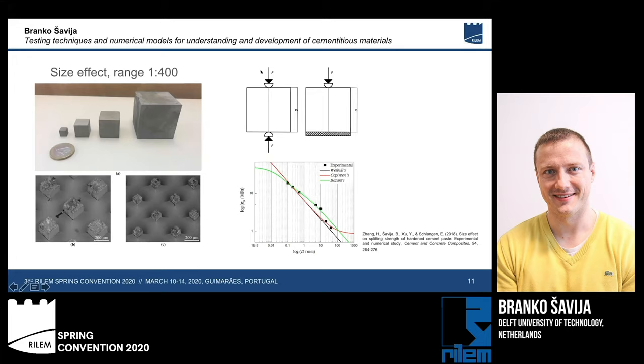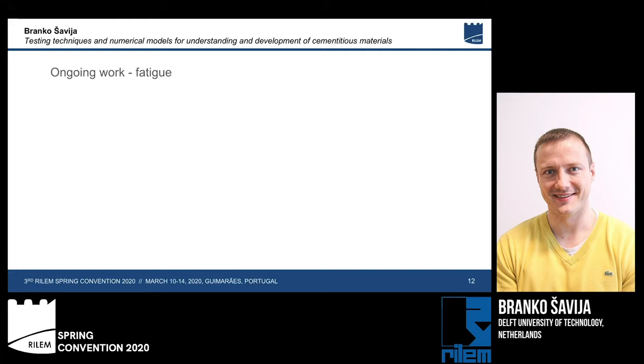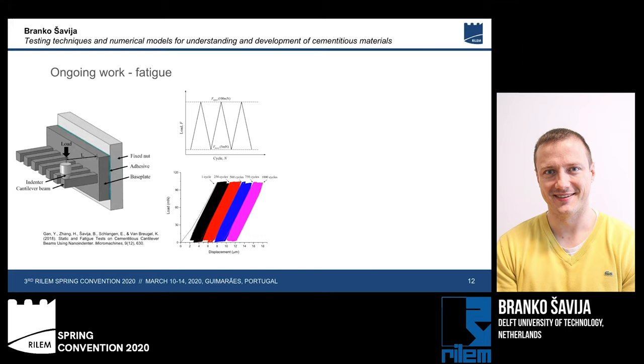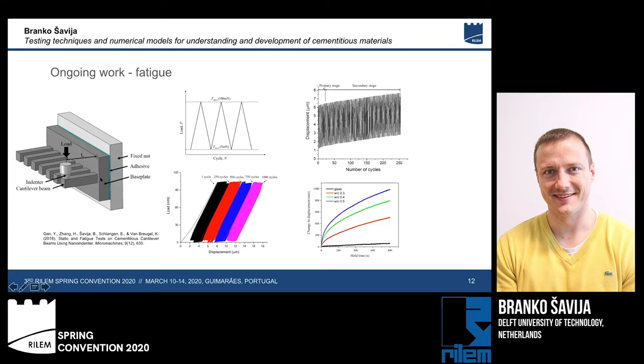Now, at the moment, we are trying to expand this work to study non-static loading, to study fatigue. So we are performing fatigue experiments with cyclic loading on these small microbeams, starting from the cement paste and going to the ITZ. So we do repeated loadings until the specimen fails and try to understand what happens. Now, what happens is unexpected, but when you think about it, it could have been expected, is that we have a lot of creep occurring in these specimens. So actually, first we need to understand the creep and that we are doing at the moment. When that is finished, we will go back and study the fatigue.